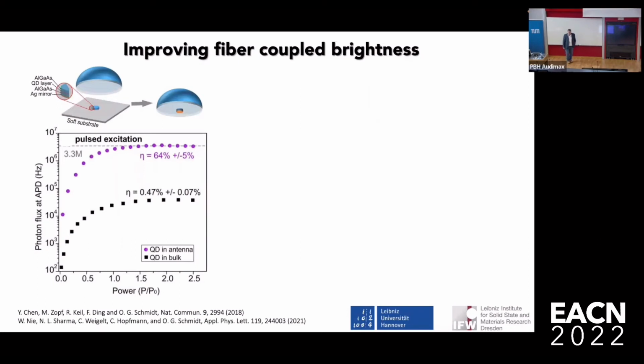Other members of the consortium are going with this kind of broad bandwidth, enhanced coupling into fibers perspective. There you can see two works which come from Dresden and Hanover. This is the work from Dresden, where they take droplet epitaxy quantum dots, fabricate gallium phosphide solid immersion lenses, and fix these samples on the backside of the lens. By controlling the thickness of the PMMA spacer between the lens and the chip, they can enhance the photon flux actually emitted into the fiber. Here you see an example of a planar sample with no nanophotonic solution.